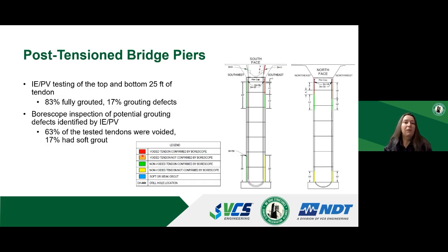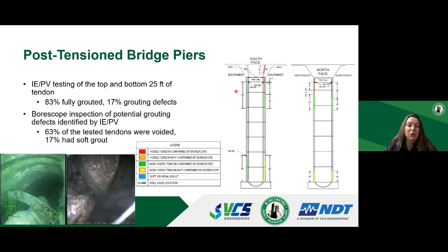Next, please. Our testing focused on the 25 feet of the tendons at the top and bottom of the piers. And for B tendons in the river piers, because they extended into the girder, we were also able to test them inside the girder. We performed impact echo testing that was followed up by borescope inspection. As Pratik mentioned, impact echo testing can't differentiate between different types of defects.